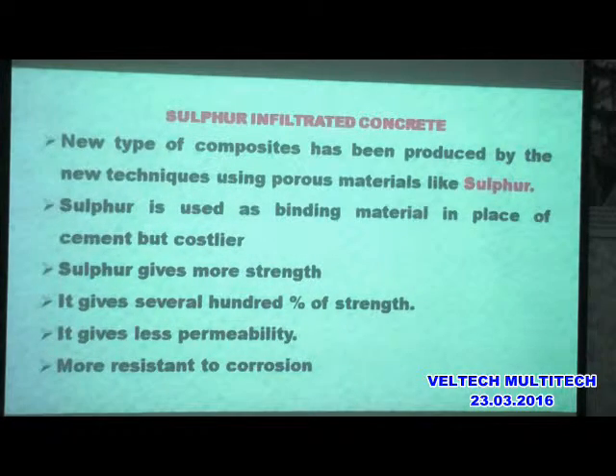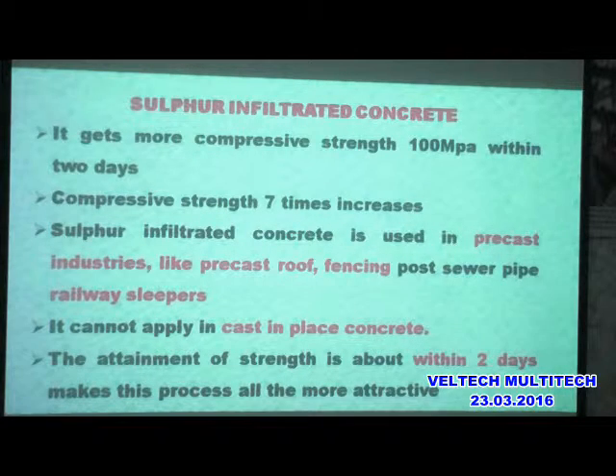The sulfur gives more strength. It gives several hundred percent of strength. That means, for example, to prepare M100 or M120 concrete also, we can use this sulfur infiltrated concrete. But it is more costly, and it gives less permeability and more resistance to corrosion. The sulfur infiltrated concrete gains strength quickly, within 2 days. You need not keep this in water. Once this liquid is poured in the concrete, you have to allow that concrete to reduce its temperature. That period is nothing but the curing period.